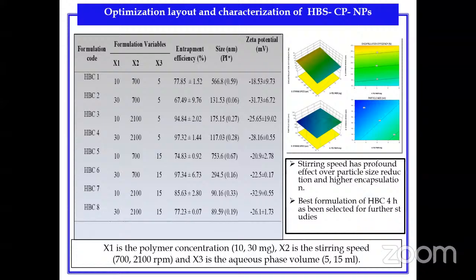of entrapment efficiency and particle size has been considered. One is stirring speed, which has a certain effect on that particle size reduction as well as encapsulation efficiency. So we also considered polymer concentration in 1:2 ratios and stirring speed between 700 and 2100 RPM. So within that, we could see that loading will be a function of reduction of the size of the nanoparticles with respect to stirring speed.